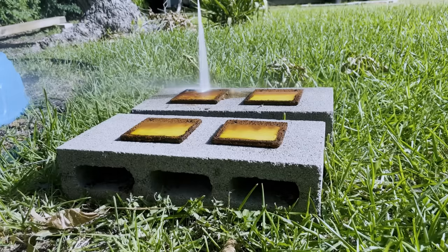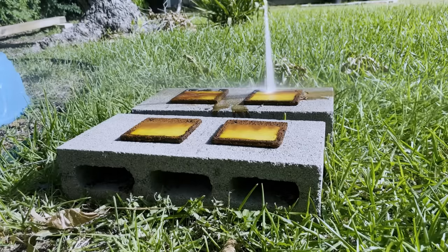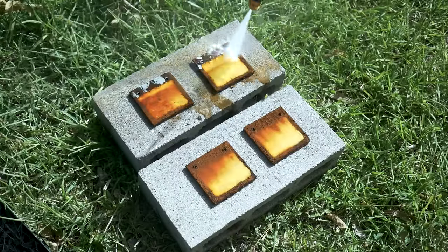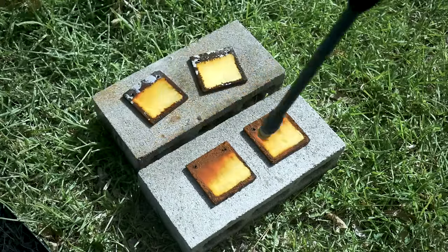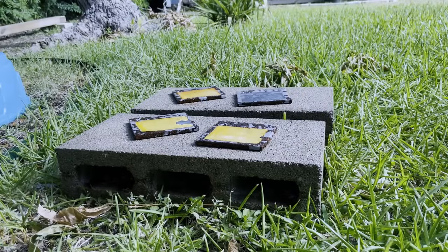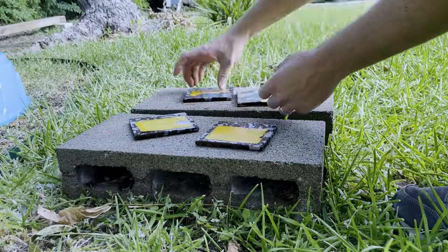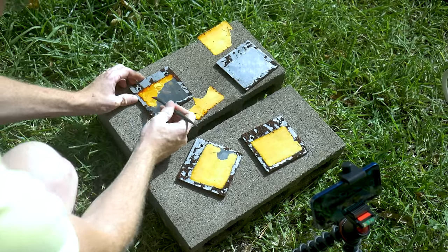But the real difference was visible once the samples were cleaned up. I used a pressure washer to blast off some of the rust, and this was enough to remove the epoxy coating on all the samples except the rough and clean one. That sample took a little more effort to remove the coating.